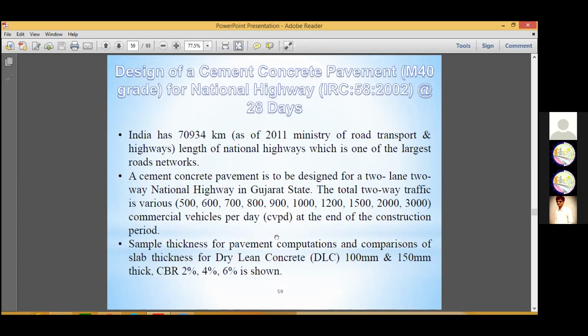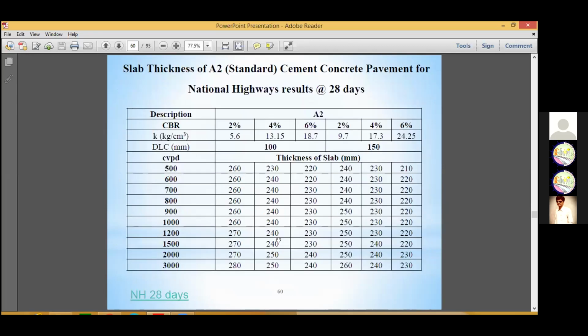Another variable is dry lean concrete, DLC, 100 and 150. And also another variable, 2%, 4%, 6% CBR value. So in a national highway, we go for the CVPD, dry lean concrete, and the CBR. Now you refer to this table for the standard concrete A2 with the 28 days results of the concrete, and then we analyze and design the slab thickness. You refer to this Table A2, the description is A2 is a standard concrete. K, CBR is at 2%, 4%, 6%. It's the value of the CBR, and the K depends on Table 1.